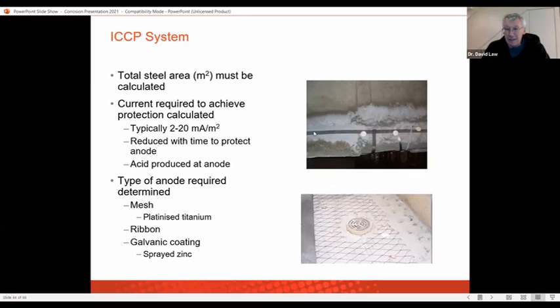And this at the top, you can see a typical anode ribbon. At the bottom, you can see a typical anode mesh. And so what we found was that we had failures of the anodes, which were failing first. We've realized that now, that as soon as you've got this passivity, you want to turn that current down as much as you can, but maintain the protection over time.